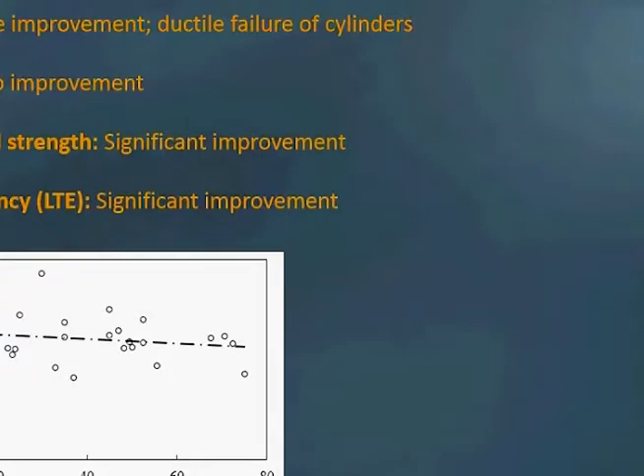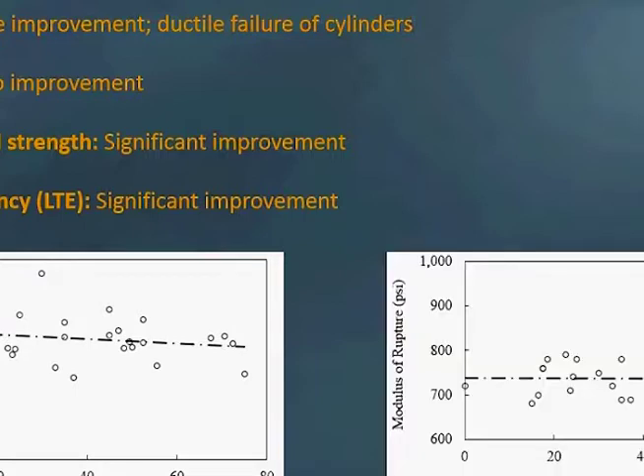Now since this country likes synthetic fibers, I'm focusing more on synthetic fibers. In steel fibers we saw we can increase the modulus of rupture or the compressive strength, but if we use synthetic fibers, we really cannot. We cannot even increase the modulus of rupture. Now pause and think for 5 seconds. The current design procedure says let's increase the modulus of rupture by 20%. But we are using synthetic fiber that does not increase the modulus of rupture at all. So we need to look at it.